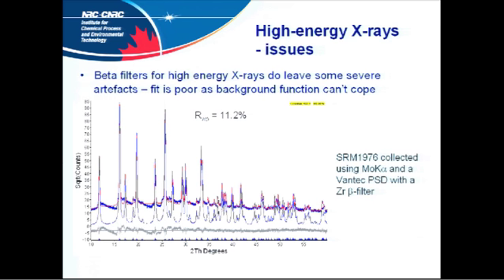Now, the one thing that does crop up with high energy systems more than, say, copper, cobalt, or any of these other ones, is if you actually use a beta filter, you do get these rather nasty artifacts. Basically, the absorption edges from the beta filter do start doing some rather weird things. Absorption edges, sort of like little tails here, there, and everywhere. And it's pretty difficult to fit on a conventional basis.